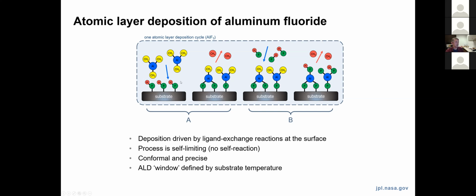So you introduce your precursor chemical, in this case, trimethyl aluminum. It reacts with the surface that you're trying to coat, creating some byproduct, which is purged out in this intermediate step. And then you introduce your second reactant, in this case, HF, because we're interested in depositing this fluoride material. And it also reacts in a self-limiting manner. In other words, these species react only with the substrate and not with each other and not with the byproducts that are formed in this process.